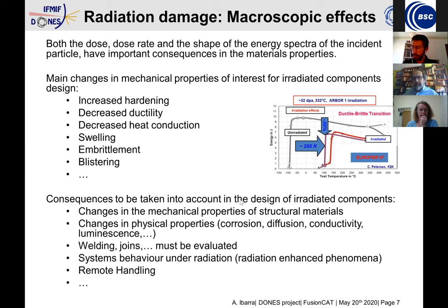We must be aware of what happens due to the radiation effects in welding and joints, and in any kind of dissimilar materials areas, because these areas usually have a high density of defects, and as a consequence radiation effects can have an impact there. We need to take into account that the system may behave differently during irradiation than before irradiation. If we change the physical properties, that means that if a system should react to a signal and this signal changes during irradiation, maybe the system will not work properly.